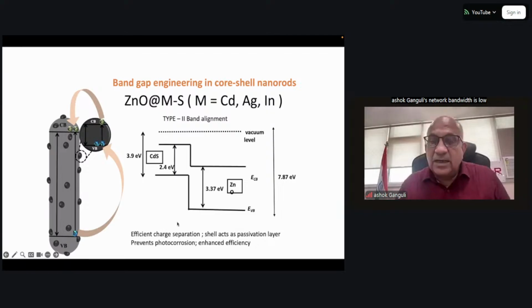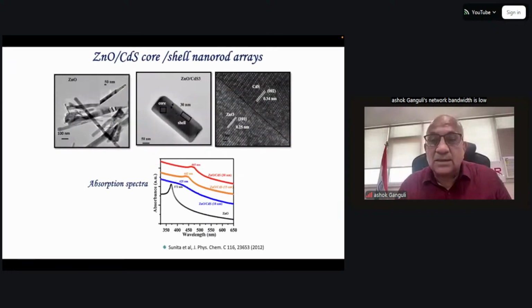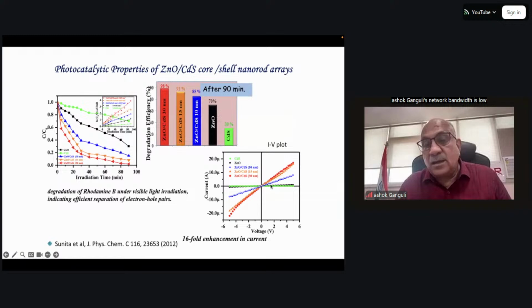So this we did long back. The paper was published in 2012, but it was quite a well-cited paper, and we could show that with changes in the thickness of the second semiconductor on top of the first one, we could change the band gap from UV to the visible region, and that enhanced the properties, which you can see here. You can see the photocurrent. The red ones have more shell thickness of the mid band gap semiconductor, which is cadmium sulfide.